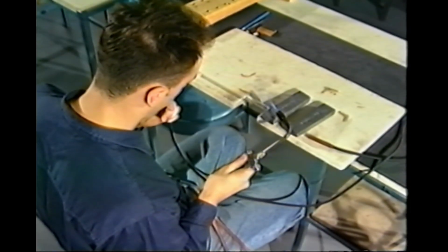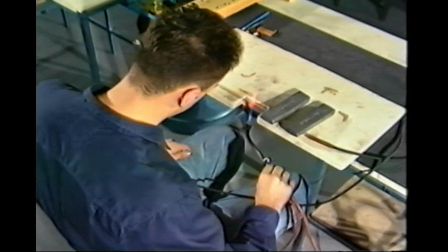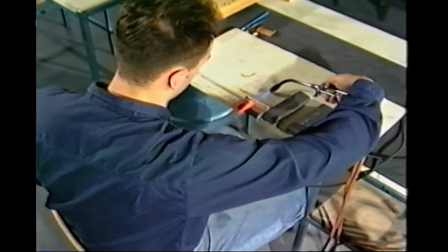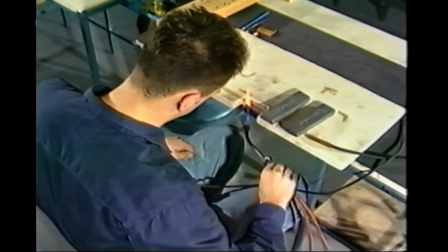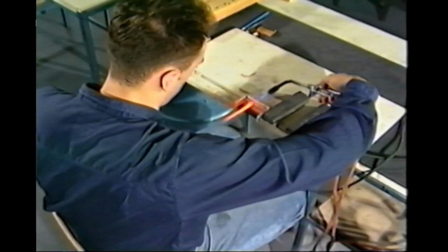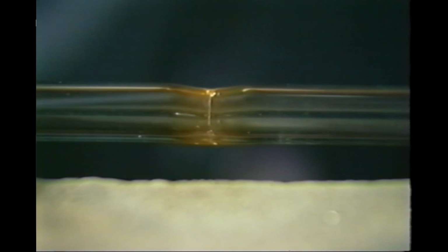Adjust the hand torch down to a small, sharp, bright blue flame. Begin melting, pointing the flame at the joint line and fully rotating the hand torch back and forth at speed to again effect full melting right around the joint until the heated area glows bright red. Because the flame is rotating and not the tube, gravity will have an effect on the melting glass, and the hot glass on the underside of the joint will sag down, and the hot glass at the top of the joint will collapse.